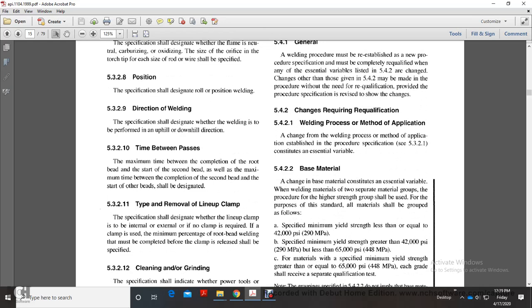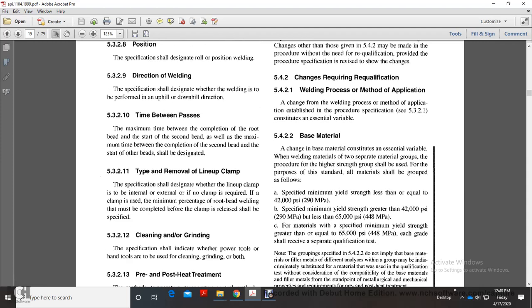5.3.2.11 Type and removal of line-up clamp. The specification shall designate whether the line-up clamp is to be internal or external, or if no clamp is required. If a clamp is used, the minimum percentage of the root bead that must be completed before the clamp is released shall be specified.